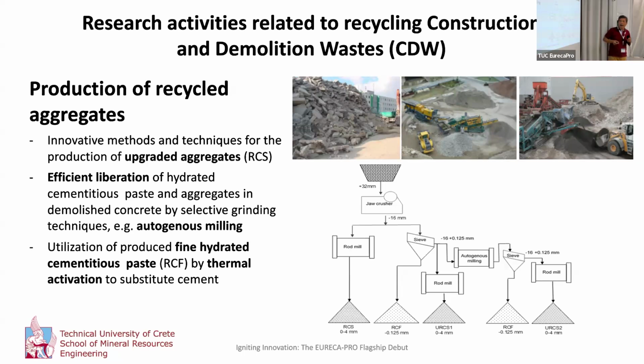If we want to produce upgraded aggregates, we have to make some additional treatment. This means that we have to design and construct a more sophisticated crushing and sieving system and to separate selectively the mortar and the primary virgin aggregates. And this is a field where we have already developed research activity, but we focus not only on the production of upgraded aggregates, but also we have to find a way to utilize the fine waste that is produced during the liberation of these aggregates, because the cement paste is much more brittle than the aggregate, so it is forming a very fine fraction which has to be utilized.